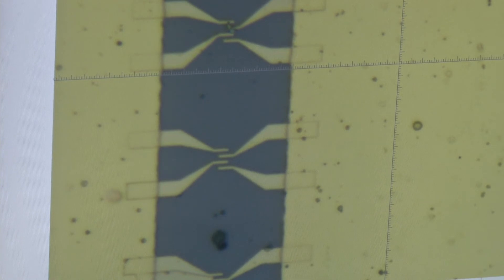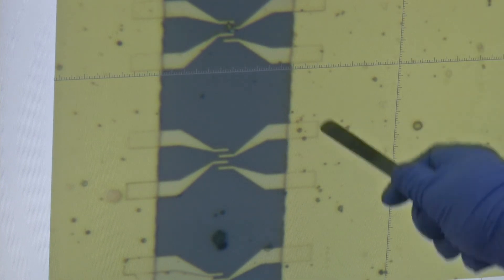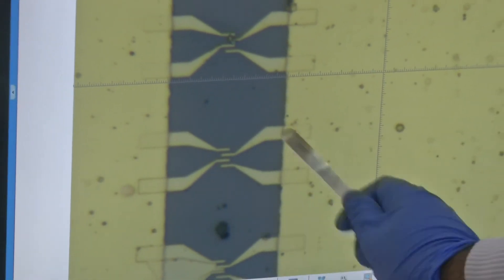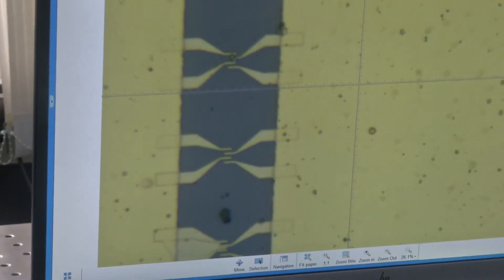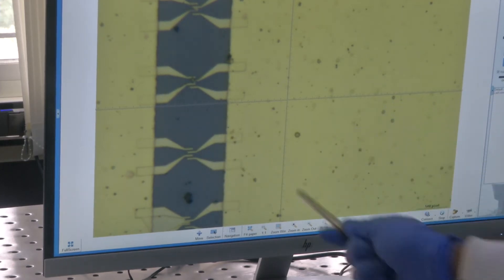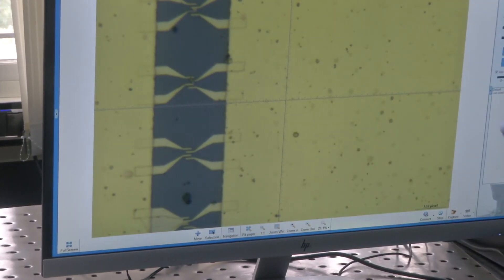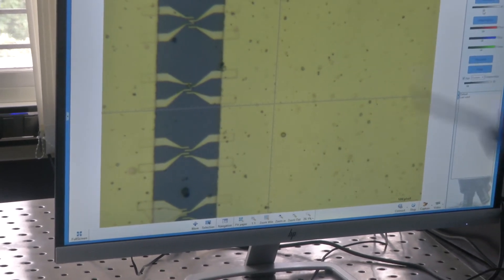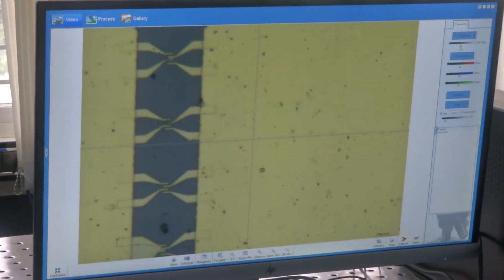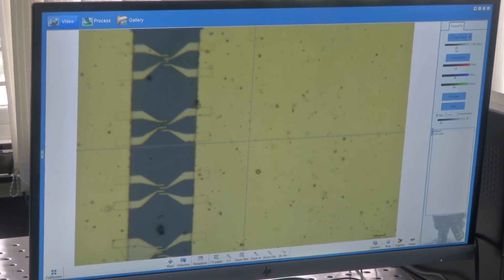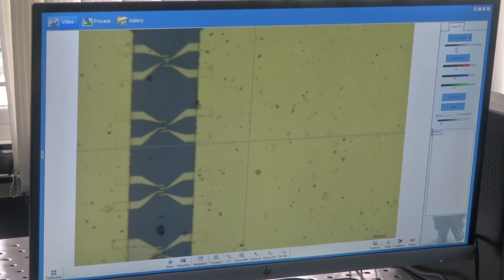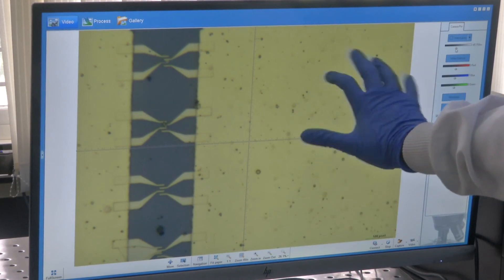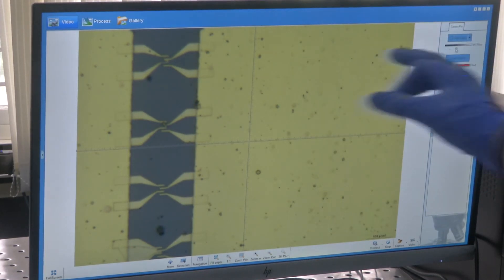These are all 200 nanometer thickness, 200 nanometer width and spacing interdigitated electrodes. These can only be made using e-beam lithography. This sensor was fabricated using a very special process where we have combined both optical lithography and e-beam lithography. These major big lines were made with optical lithography, and these small lines were made with e-beam lithography.